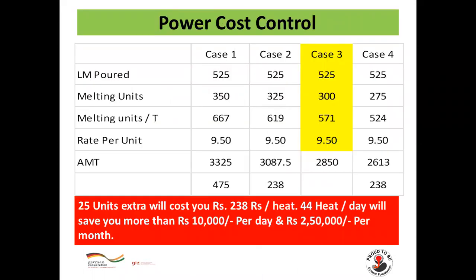These are 4 case studies I have shared with you with the power consumption of the furnace. You can see 350, 325, 300 and 275 units per heat. So if you consider benchmarking, then you can see 25 units extra will cost you about 238 rupees per heat. If you consider 44 heats per day of 500 kgs, it will save you more than 10,000 rupees per day, which will be around 2,50,000 rupees per month. So 2,50,000 per month is a huge saving just by saving 25 units per heat.